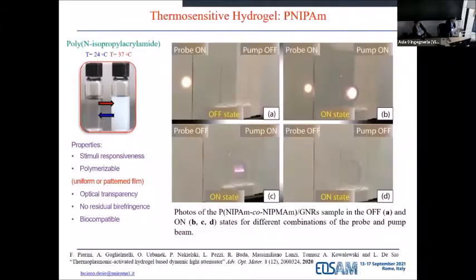Moving forward with the devotion to make bio-related applications, we decided still to work with thermosensitive materials, but with less complexity and essentially water-based. We combined golden nanoparticles and hydrogels. Those are thermosensitive materials, and very easily you can see that the material is water-like at room temperature, but when you heat up close to the body temperature, the material turns out to be cloudy, like milk.